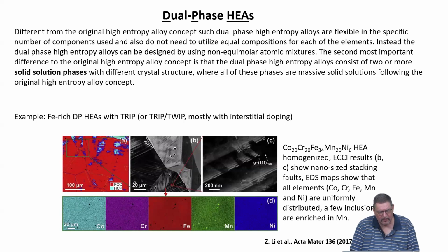And one aspect here which people emphasize is that in these 2-phase, dual-phase high entropy systems, they can also get transformation-induced plasticity TRIP or twinning-induced plasticity TWIP effects. And this is what you can find in these high specialty steels, which are very expensive. So there you pay by kg and not by ton. But this is what saves your life, for example, if you drive an expensive car too fast and you get an accident. Because these mechanisms can absorb huge energies, and this transformation can occur very quickly. So it's also a process which occurs at high strain rates. And this is why this is so beneficial to use materials which can show this type of effect.